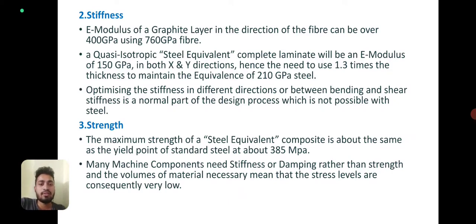And the third most important characteristic of composite materials is strength. The maximum strength of a steel equivalent composite is about the same as the yield point of standard steel, about 385 megapascal. Many machine components need stiffness or damping rather than strength, and the volumes of material necessary mean that the stress levels are consequently very low. Here we can see the graph between tensile stresses and equivalent stresses.